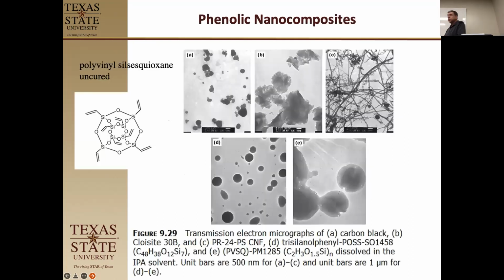Okay, so now switch gears and go to phenolic nanocomposites. In phenolic nanocomposites, they usually use phenol and formaldehyde, and that bakes out into a phenolic polymer microstructure on the foam. And in this one, what they did was they used an octavinyl POSS molecule, and what they got was phase separation. If you look at this right here, as you do different things, this one has just carbon black in it. See the carbon black's kind of all distributed, not too bad, a little bit of clumping. This is montmorillonite. We did a very poor job of exfoliating the montmorillonite, but at least some of it is spread out right here.